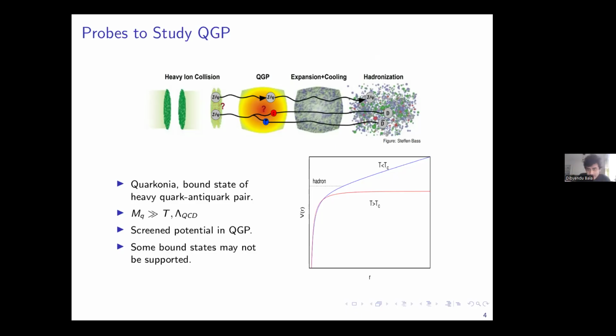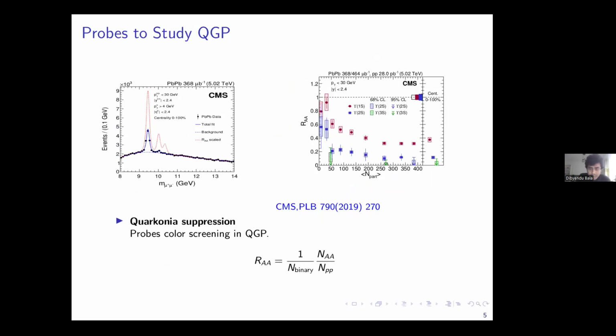As a result, the number of quarkonia that you would expect from heavy ion collision will be much smaller than what we would expect from the proton-proton collision, and that is exactly what we see in the CMS experiment. Here I have plotted the number of, sorry, it's not J/psi, it's upsilon, a bottom anti-bottom pair, in the dielectron channel. The red curve is what you would expect from a PP collision. But in the lead-lead collision, we see a much smaller value compared to what you would expect from PP. And these are the excited state upsilon peaks, and you see that they are more suppressed compared to the 1S, the lowest one. This is the sequential suppression that one would see in heavy ion collision experiments.